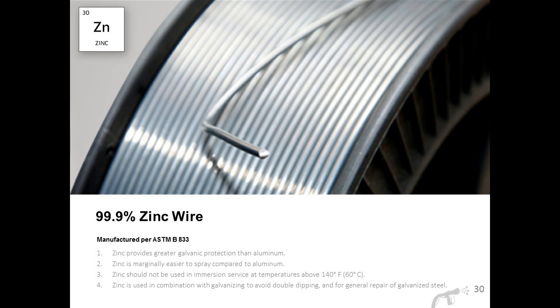One other key point to mention, and this is related to temperature, is that zinc shouldn't be used in immersion service at temperatures above 140 degrees. A good example for this would be, and again, it doesn't really have much of an impact on the bridge industry, but this would be a good option for potable water tanks, but definitely not for boilers that are going to see temperatures in excess of 140 degrees.